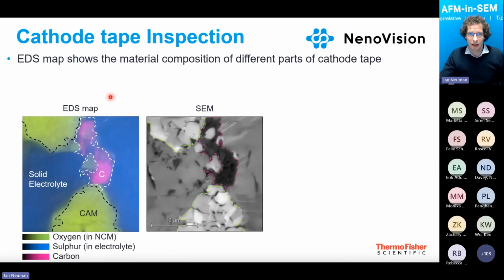When we talk about the inspection, this is what you see using the SEM, where the contrast already indicates some components. Using EDS, the chemical composition, you can directly localize and identify different components. We see solid electrolyte, which has sulfur. We see cathode active materials with oxygen, and you see carbon here. And you can see how it's correlated with the contrast.